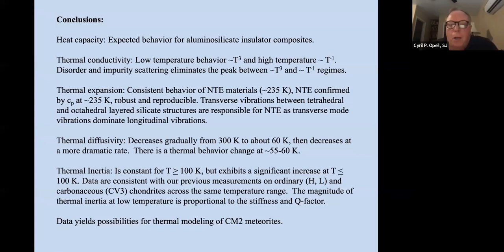So I want to say a couple of things. The heat capacity is very expected behavior for these meteorites, because they're aluminosilicate insulator composites. That's the material they are, and they're well behaved, with no major transitions. The thermal conductivity has low temperature behavior around T cubed, and high temperature behavior around T to the minus one. Also, disorder and impurity scattering eliminates the sharp peak that you would see in diopside or quartz.